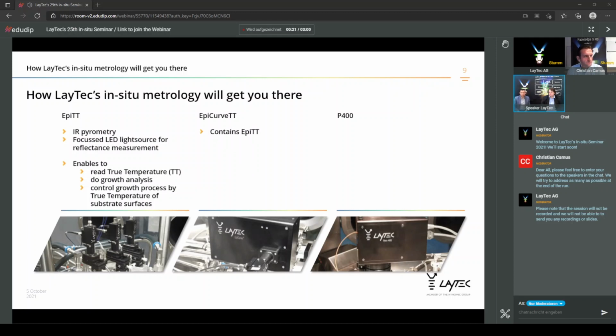The epicurve contains the same functionality as the EpiTT, and in addition, it has a focused semiconductor laser for the curvature detection. So you have the complete EpiTT functionality, and in addition, it enables you to get the curvature detection. Curvature detection means you can monitor wafer relaxation, for example, and even more, you can do the strain engineering. Especially gallium nitride on silicon requires a sophisticated strain engineering so that after you have done your growth, you have, after cooling down, a flat wafer, for example.